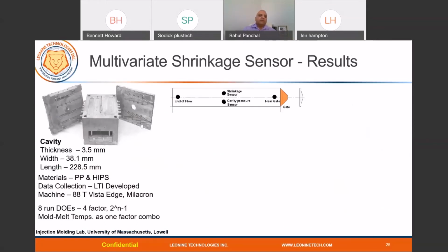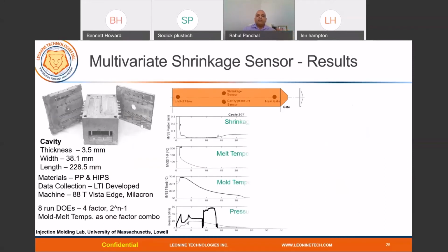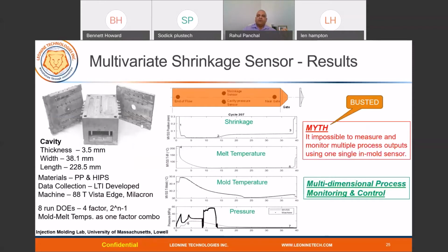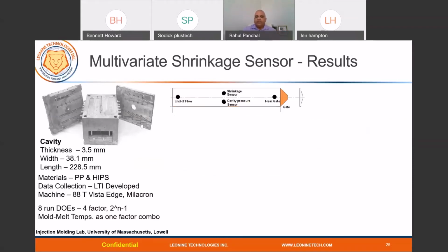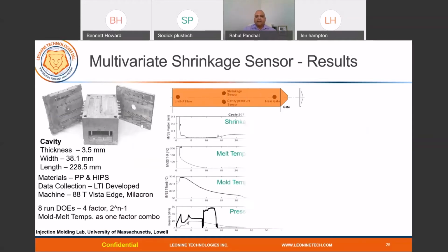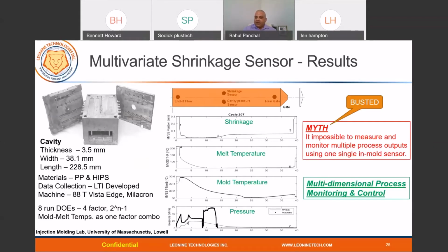So again, look at how that works. We use the same mold, but this time, instead of 1.5 millimeter and 2.5 millimeter cavity thickness, we use a 3.5 millimeter cavity thickness. So we want to go thicker. Again, you can see that as soon as the melt comes into contact with the shrinkage sensor, you can get the shrinkage, melt temperature, mold temperature, and pressure. So you can measure multiple process outputs from one sensor without having complex instrumentation.